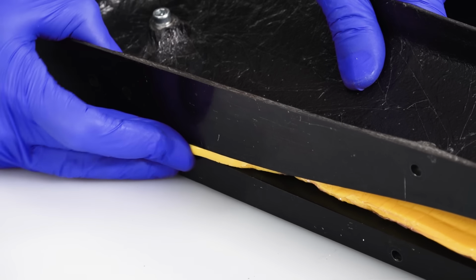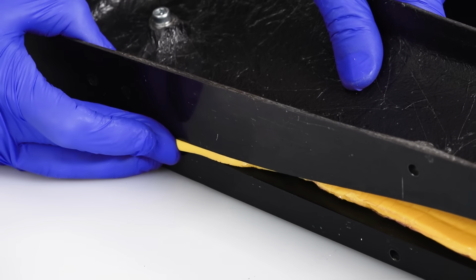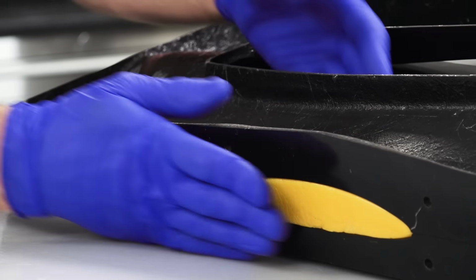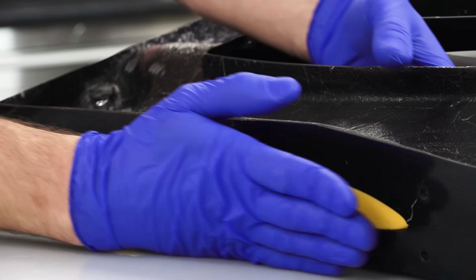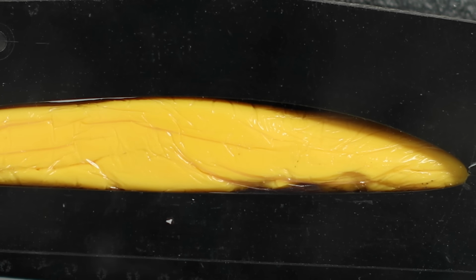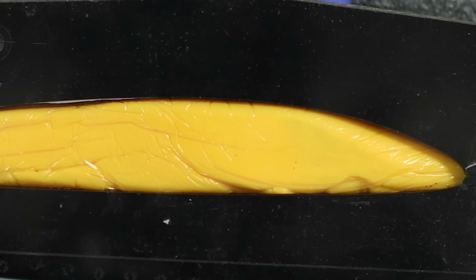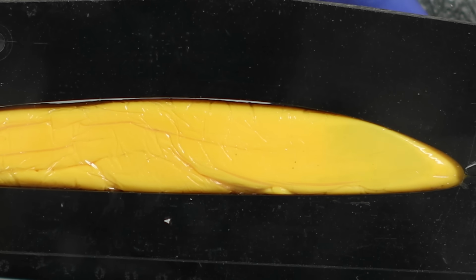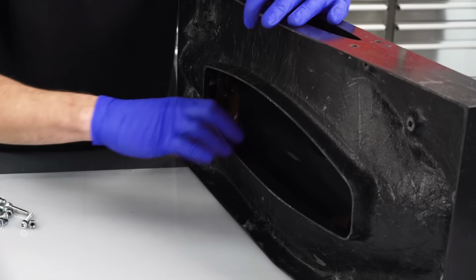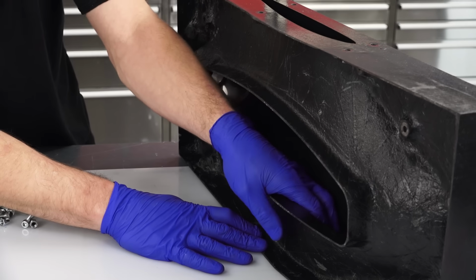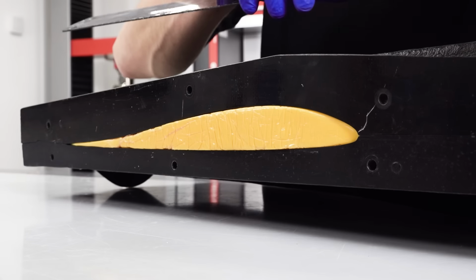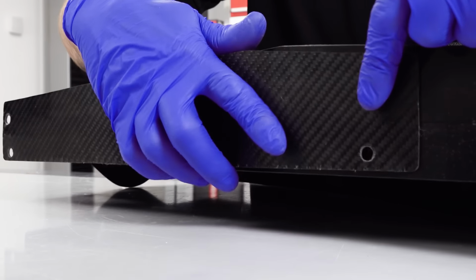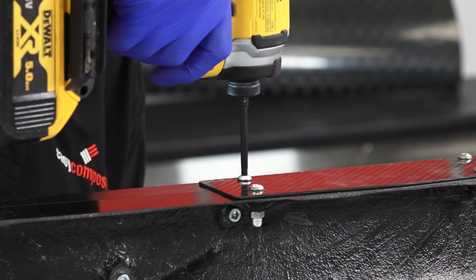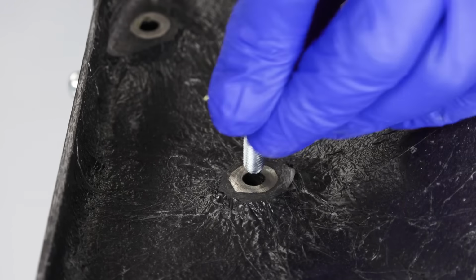To get these finished, I will now close the mould and press and blend the silicone into the mould surface. You're looking for a fillet or a feather edge here. If you were to leave a sharp transition, this may cause vacuum bag bridging in its own right, leading to a print through on the surface of the part. It's probably a bit difficult to see, but I now have all of the difficult to access areas filled with a smooth transition.